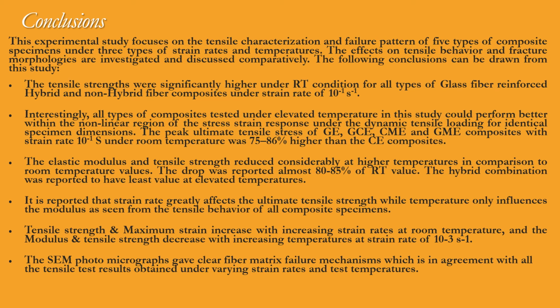Tensile strength and maximum strain increase with increasing strain rates at room temperature, and the modulus and tensile strength decrease with increasing temperatures at strain rate of 10^-3 per second. The SEM photomicrographs have given clear fiber matrix failure mechanisms, which is in agreement with all the tensile test results obtained under varying strain rates and test temperatures.